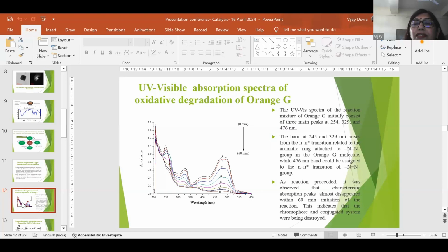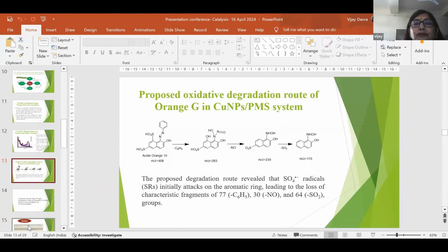As the reaction proceeded, it was observed that the characteristic absorption peak almost disappeared within 60 minutes in the presence of the copper nanoparticle, which indicates that the chromophore and conjugated system were being destroyed into harmless products. This is the proposed oxidative degradation route for Orange G in the copper nanoparticle peroxomonosulfate system. The proposed degradation route revealed that the generated sulfate radicals initially attack the aromatic ring, leading to the loss of characteristic fragments such as 77, 30, and 64 groups and conversion into harmless products.